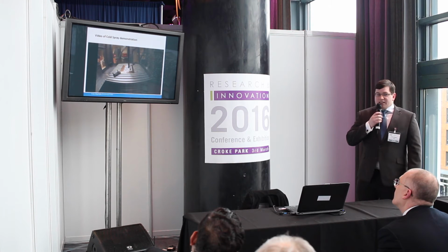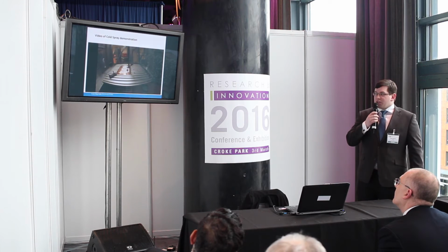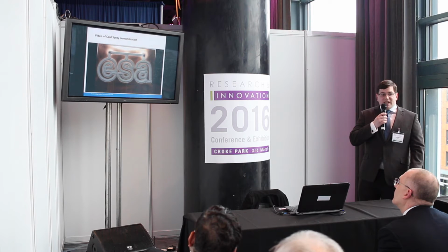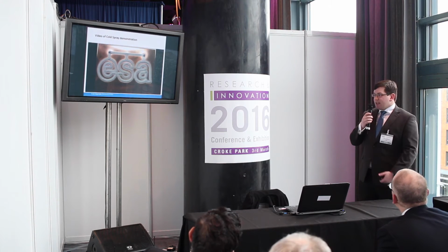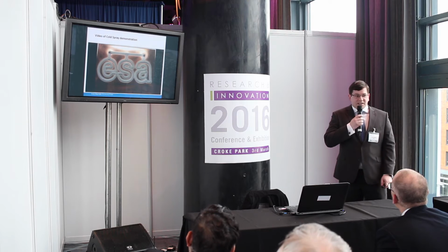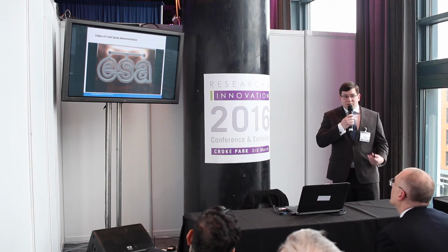And as you can see here, the deposition rate is actually quite high, particularly when compared to a lot of other additive techniques. You can put down a lot of material very, very quickly. You can put down hundreds of grams per minute if you get your parameters right and you get everything working very, very well.